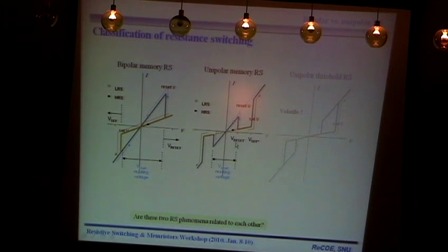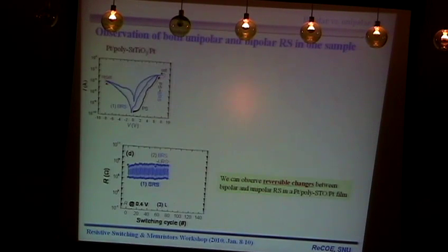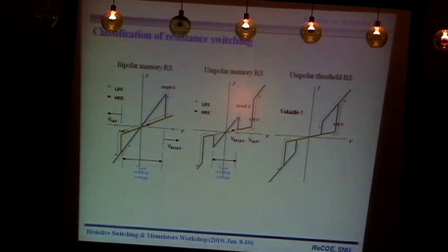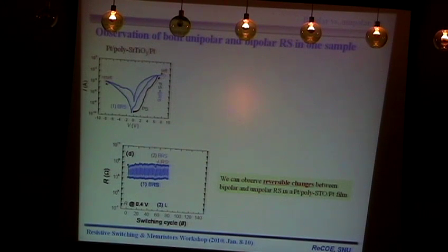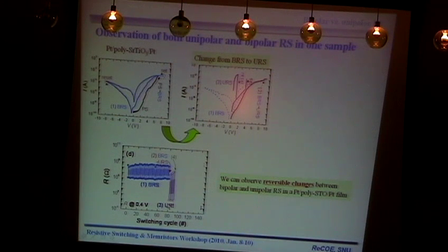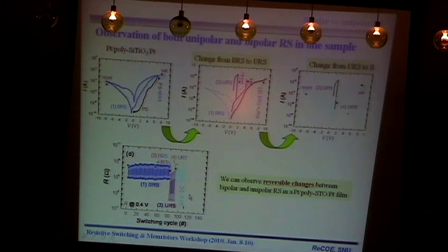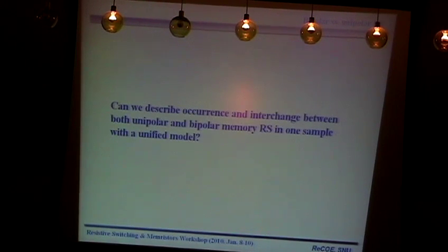Now we concentrate on these two. We are asking whether these two switching phenomena are related to each other or not. One of the reasons we raised the question was that we observed another interesting phenomenon. In one sample, strontium titanate, originally it showed bipolar resistance switching. But if you repeat, suddenly, under the exact same condition, it enters unipolar resistance switching. Then after repeating several times, it goes back to bipolar, and repeating again. How can this kind of thing happen in the system? This is a very complicated experiment, very rarely observed. So the question is: can we describe the occurrence and the interchange between both unipolar and bipolar memory switching in one sample with one simple model?